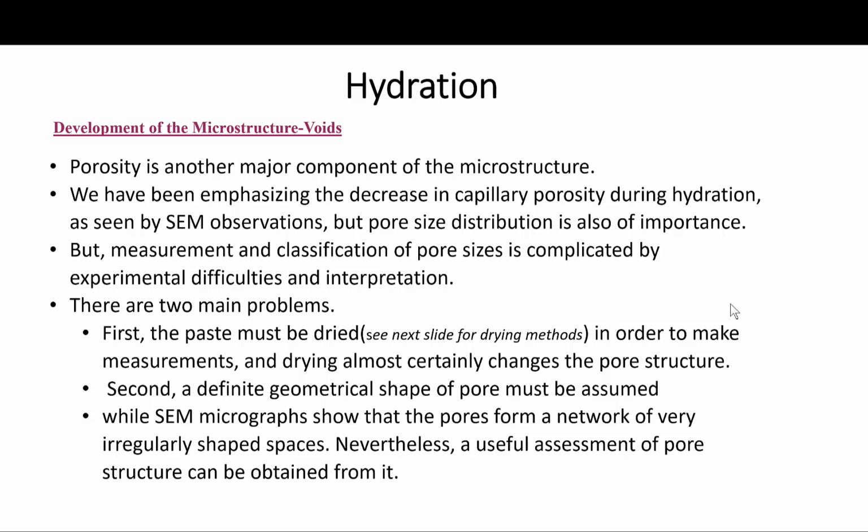Second, a definite geometrical shape of the pores must be assumed in order to do these calculations. While the SEM micrographs show the pores to form a network of very irregularly shaped spaces, nevertheless a useful assessment of pore structure can be obtained.